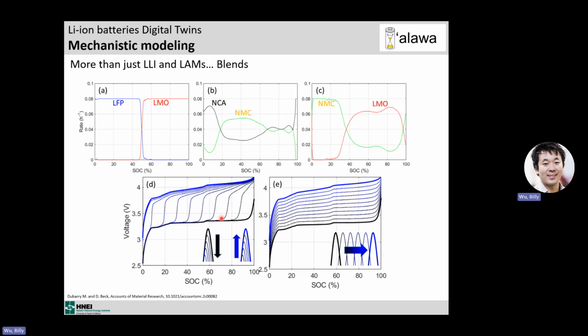In a way, if you think in terms of derivative, one peak disappears and one peak is growing. But if you have a solid solution, you're going to gradually go from one to the other. In a way, the black peak is moving towards the blue peak. Same initial point, same final point, completely different path in the middle. So we can do both.